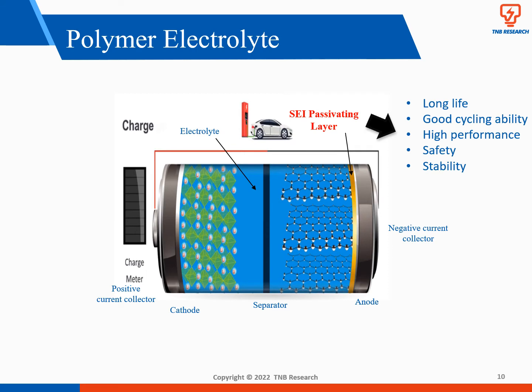In recent years, researchers have tried to improve the electrolyte and separators for lithium-ion batteries, especially polymer electrolyte with high ionic conductivity and additives, to create a protective solid electrolyte interface (SEI) layer and stabilize silicon anodes and NMC cathodes. Effective SEI is essential to improve the cycle life of lithium-ion batteries, as these additives are able to smoothen the movement of lithium ions between cathodes and anodes and prevent battery degradation, whereas ionic conductivity defines a battery's ability for ions to move through its electrode structure. In other words, a higher conductivity allows more ions to pass through at a given time and thus improves the capacity at a higher discharge rate.